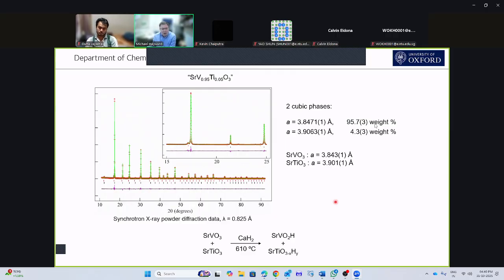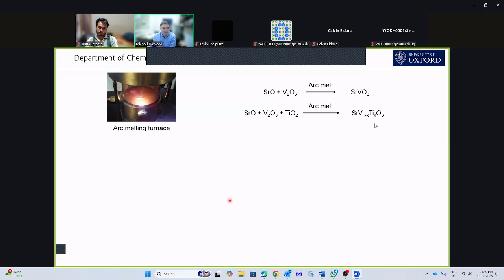Well, another way we can make this material is through arc melting. So in an arc melting furnace, basically, we strike an electric arc through an argon atmosphere. So we get an argon plasma, which is at a temperature of something around 3000 degrees C. So what that does is that melts our materials. And so we can make SrVO3 by melting strontium oxide and vanadium oxide together. So we think we could make this doped material by melting the vanadium and titanium together.